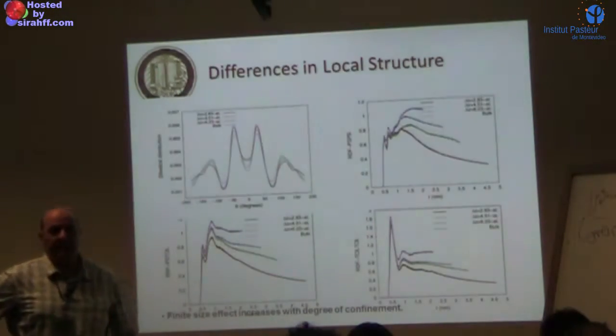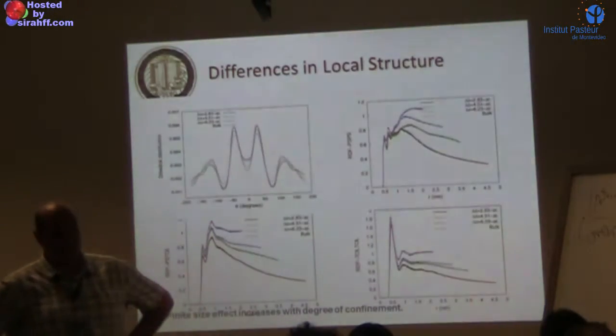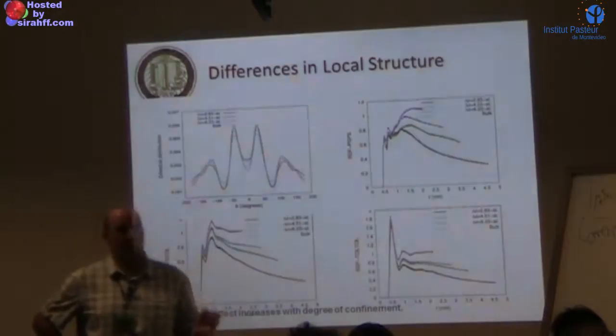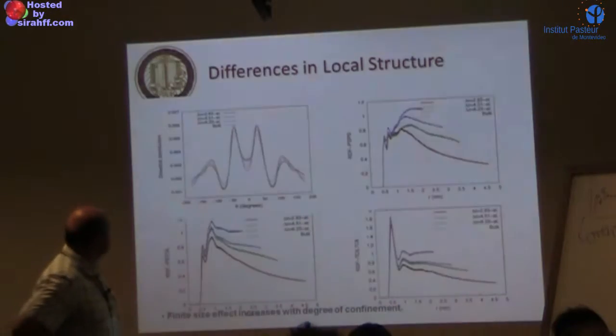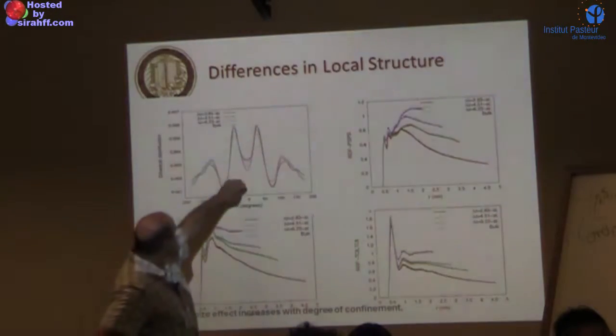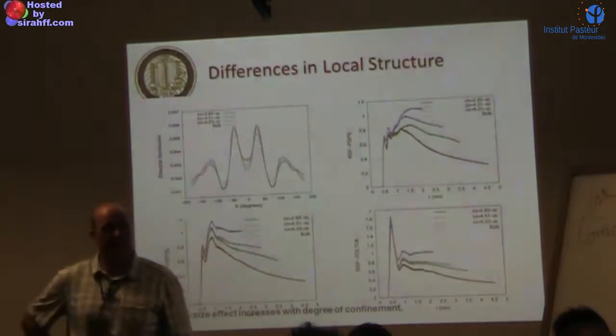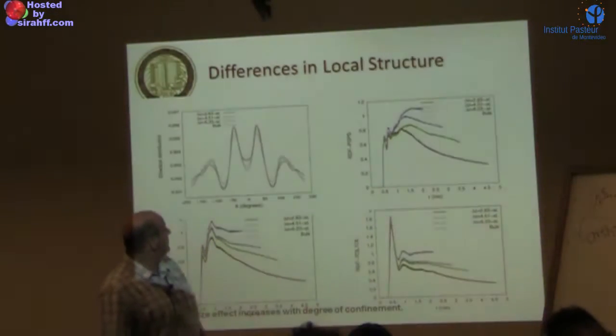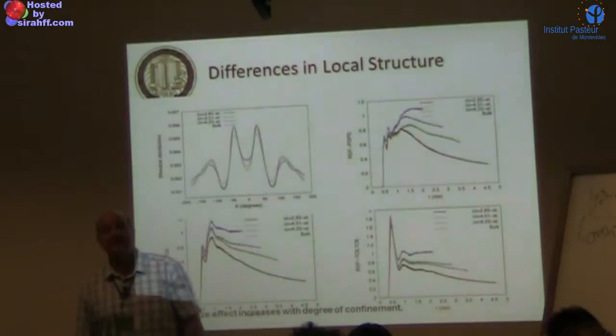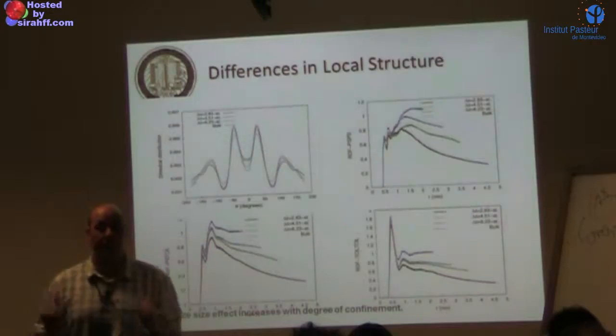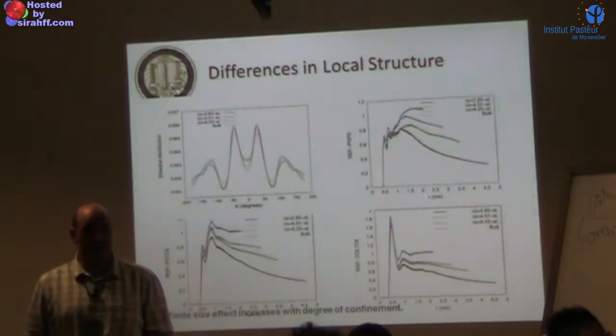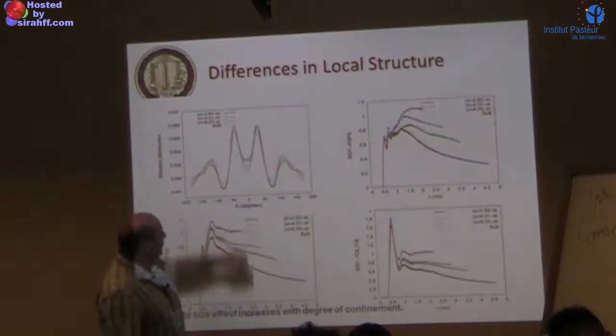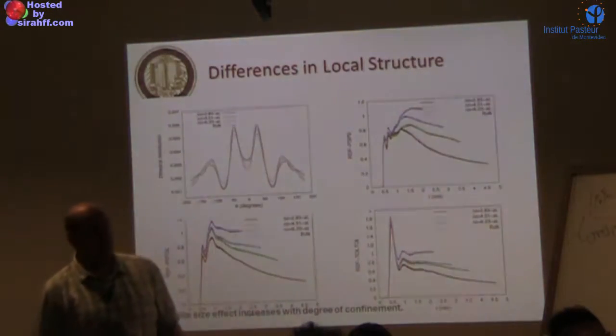We simulated atomistically with three different slit thicknesses in the nanometer range. We used the middle thickness to parameterize the coarse-grained model, then used that model to simulate the other two confinements. Even intramolecularly, the dihedral angle distribution — the softest intramolecular degree of freedom — changes with confinement. When compressed to 4.5 or 2.8 nanometers, the average polymer conformation changes, which is bad news.